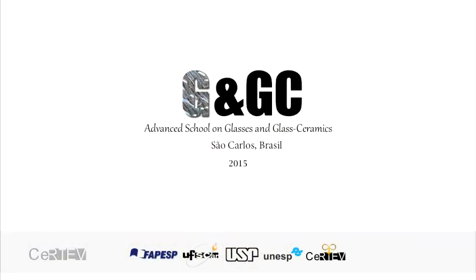but is there any theory which can at least describe this qualitatively, although not quantitatively? And to get this information from this relation, I am showing you two contrasting facts about ion dynamics in glasses. Here you can see silver metaphosphate glass, in which we have silver iodide doping. You can see the drastic change in conductivity from no doping to a fraction of 0.6 mole percent. There is a change in conductivity by 5 orders of magnitude, and this is what is called fast ion conduction.